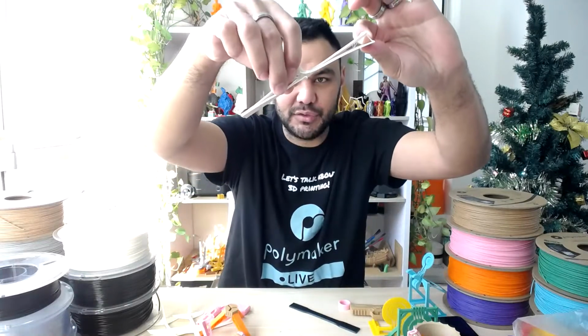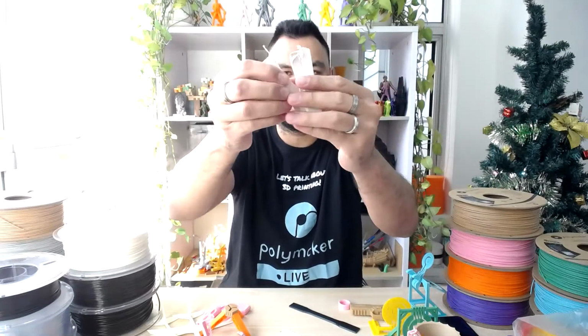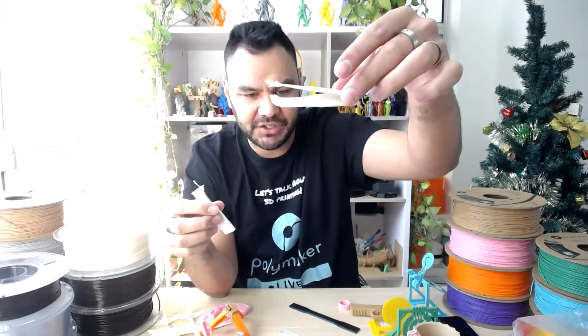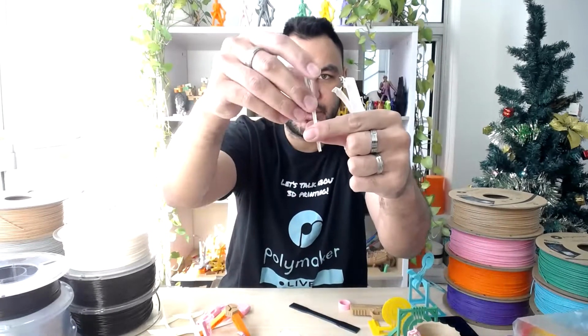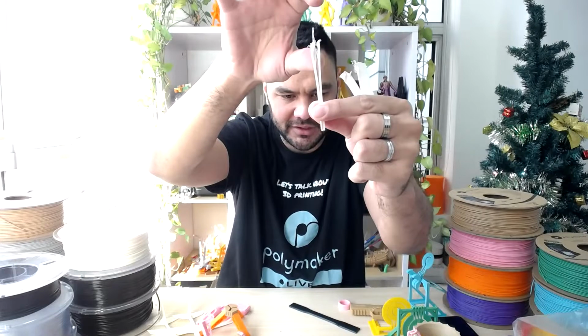I basically have two sample parts at this point. And now I get rid of it. So I end up with a big delamination here and a beginning of delamination here. A fair amount of delamination already. If we had to explain this, first, the gum feeling comes from the ductility that is added with the ABS. The delamination, my guess, is because these parts were printed on the Ender 3, so no heated chamber, and this one requires at least an 80-degree heated chamber.